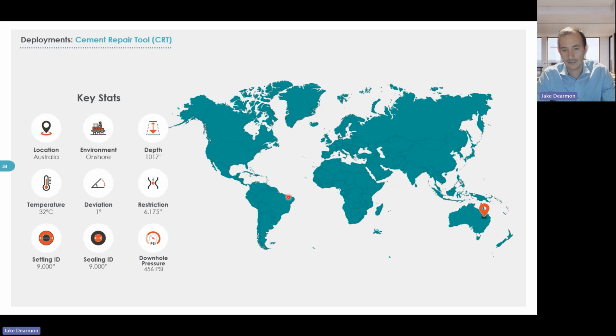those microannuli and channels. The benefit of using BiSN over a traditional squeeze job would be the low viscosity of the alloy. We don't have to rely on high injectivity rates like you would with a resin or cement to actually get the material into those fissures, through those tiny perf channels, into those cracks in the cement. The low viscosity of the alloy itself, coupled with the high density, allows it to do that.